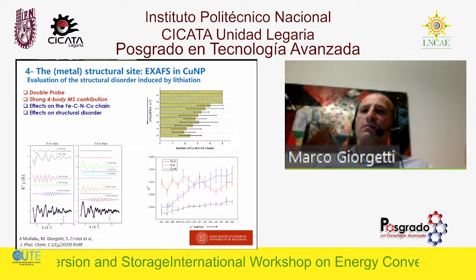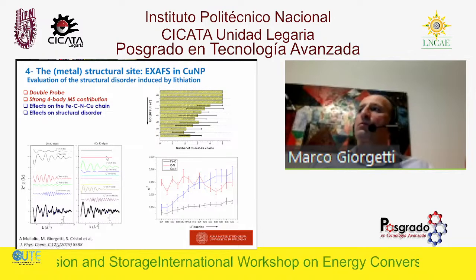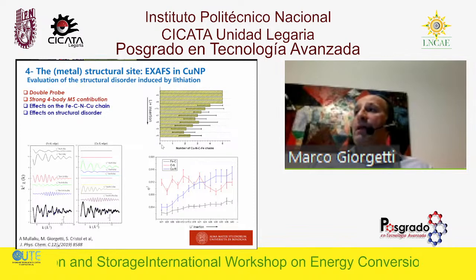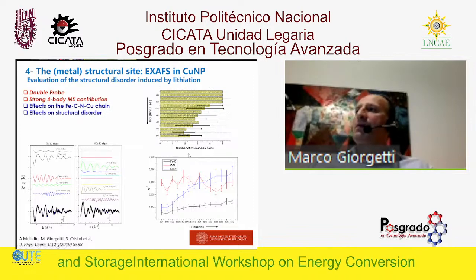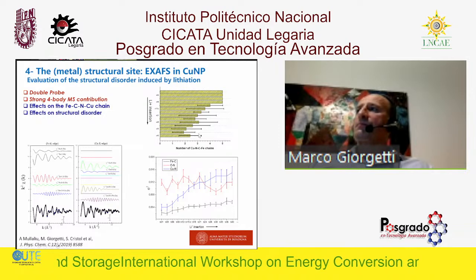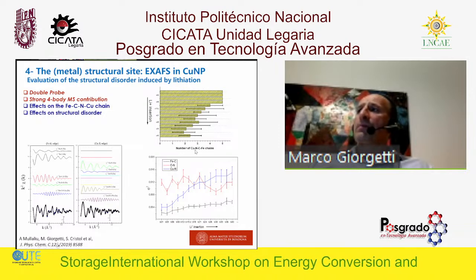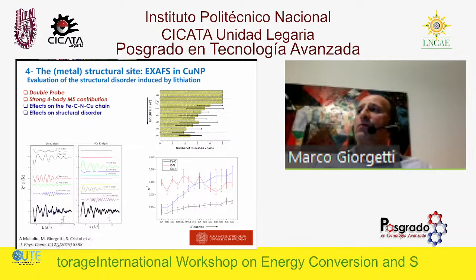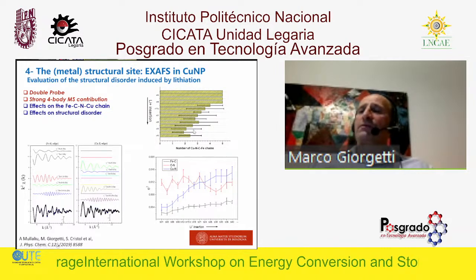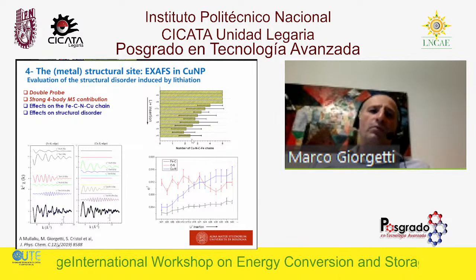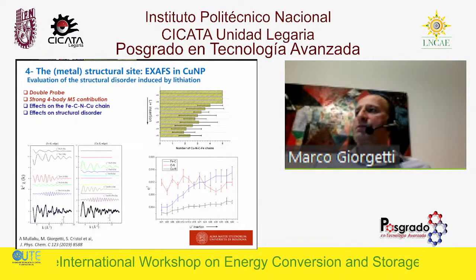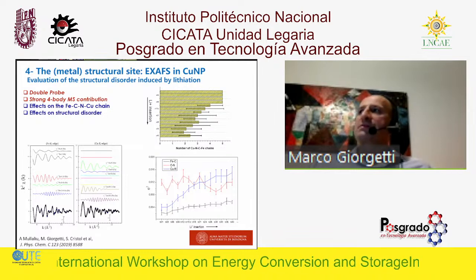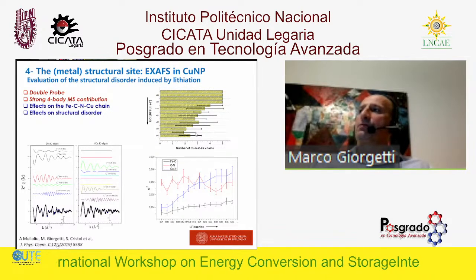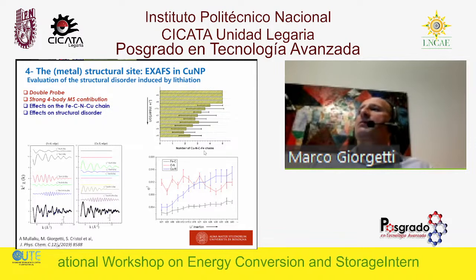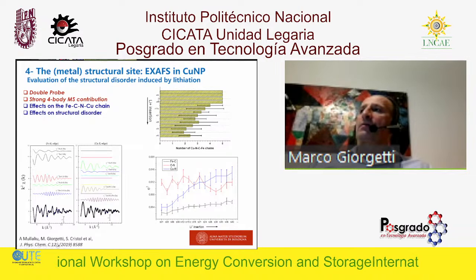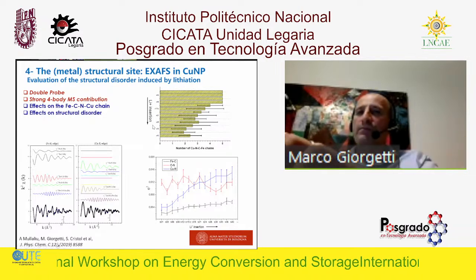The other fact is, because of that superfocusing effect, we were also able to try to check the number of chains. That was a very difficult exercise, actually. We found that these copper, nitrogen, carbon, iron chains during the lithium insertion were kind of modified. So probably we don't have the proof by looking at the oxygen, the water, residual oxygen that we have inside. But anyway, we were able to check that the number of chains of the copper, nitrogen, carbon, and the iron is changed during lithiation.